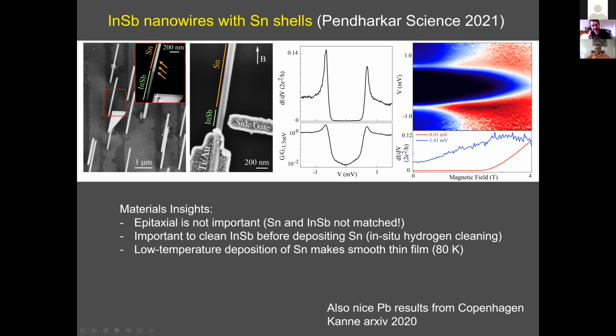Zoom works well, huh? Okay, so it's the same nanowire, but we varied the superconductor. We worked with aluminum, we worked with niobium, now we work with tin. Tin is a well-known material, of course, but never been used in this context. And it's a beautiful thin shell of tin. You can't even tell where it is. I have to draw this line for you to indicate where tin is. So it's very thin, like 7 nanometers of tin or 15 nanometers on this 100 nanometer nanowire.